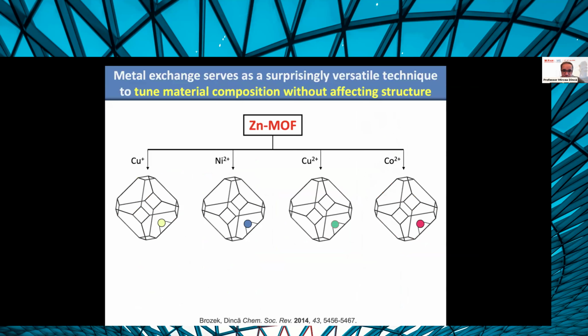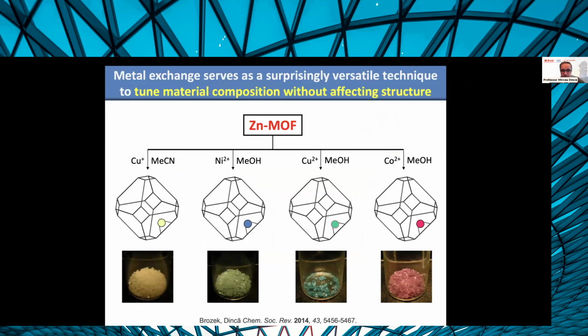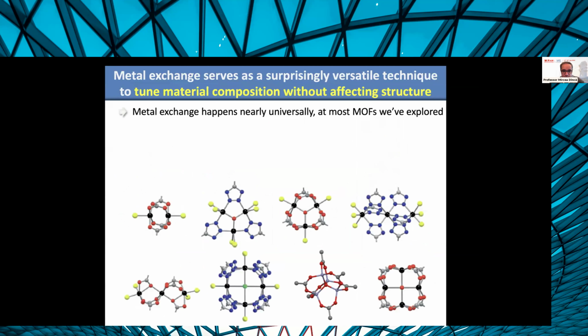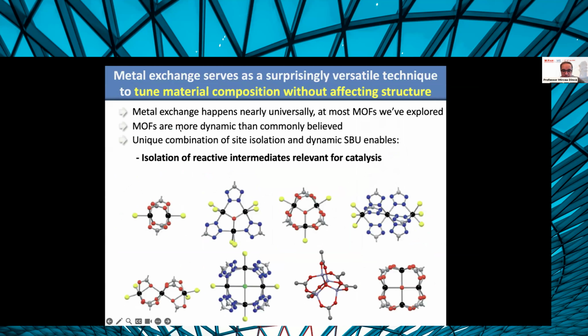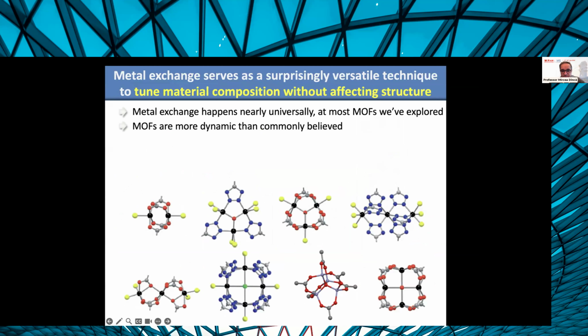And that enables something very important that my group takes advantage of a lot, which is metal exchange. You can literally exchange metals from the solution to the SBU. So now you can rationally tune the composition of MOF by saying, if I take a metal node, an SBU, and it is naturally self-assembled with manganese or zinc or copper, what have you, but I like that metal center because it has, say, 2 open coordination sites or maybe 3 open coordination sites, but I'd like to have nickel there or titanium or chromium.